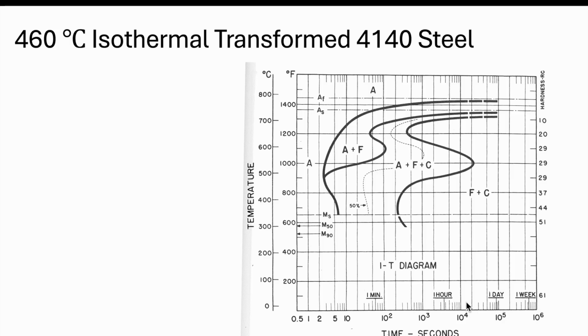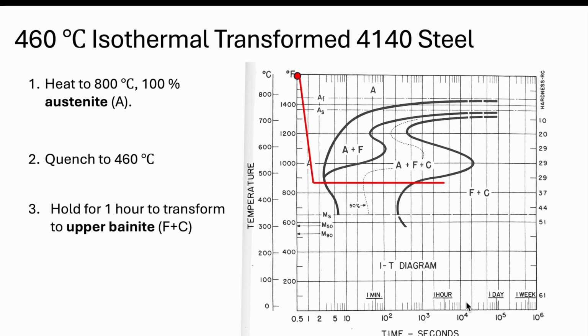All right, so again, we're going to go up in temperature. And so the next one I want to hit is 460. We do this in the lab, and so I think this is another useful one to see. So start the same way, start at austenite, rapidly cool to 460, hold there. And you kind of get from the perspective of what we're doing, we're trying to fully transform them at the temperatures we're at. So here we need to go to, again, about an hour before this fully transforms. So the overall process is the same, goes from austenite to austenite plus ferrite plus cementite until we just get ferrite plus cementite, like about an hour.